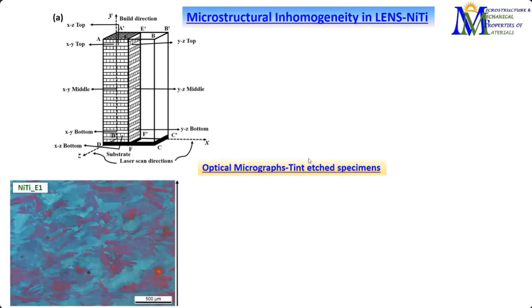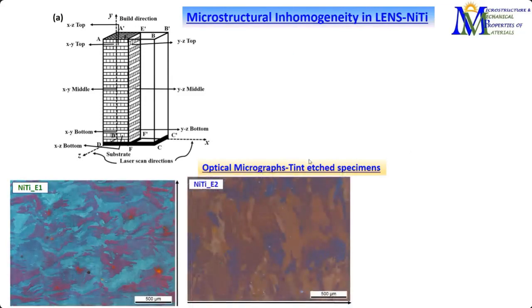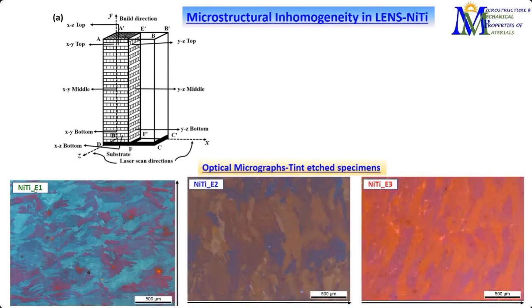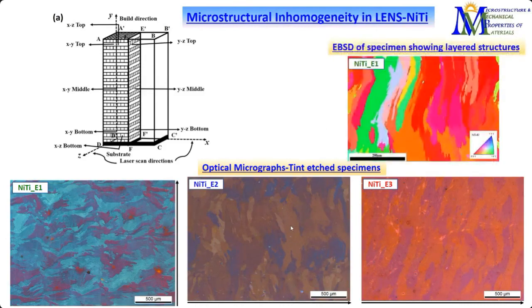For a particular location, we've named these E1, E2, E3, where E1 is made with the lowest energy and E3 with the highest energy. We can see there is a complete difference in the microstructure. This is the typical optical microstructure in the tint-etched condition, showing how we can generate this colorful microstructure optically.